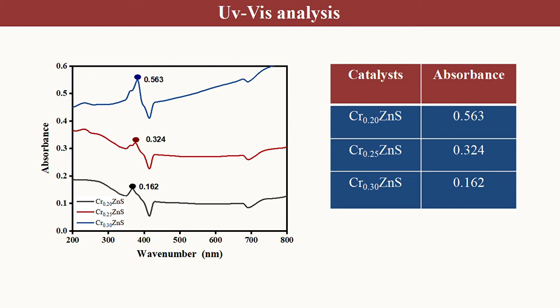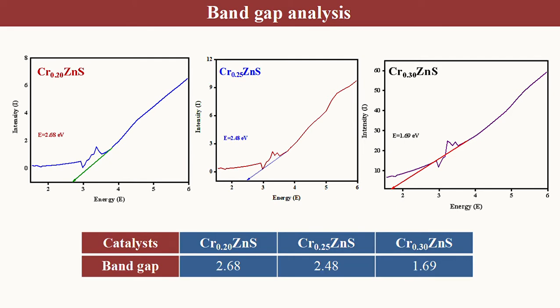The concentration of doped chromium had a pronounced effect on the optical properties of the zinc sulfide catalyst and witnessed a significant redshift in the absorption of chromium-doped zinc sulfide. The bandgap values of the samples are inversely related to the doping concentration of chromium. As the concentration increased, the gap energy decreased from 2.68 to 1.69 electron volt.